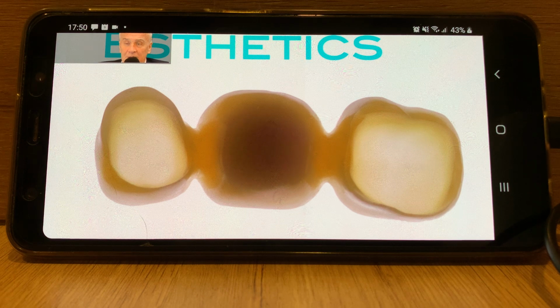Here's another material. This is also zirconium. This is also a marriage of two different strengths of material. This happens to be 5Y, the very 650 type material in terms of flexural strength, but the body in this case, because it's being used for the posterior, is 3Y zirconium. So that is the regular zirconia and the strongest zirconia that we have at the present, and that has about 1,100, 1,200 megapascals of flexural strength.